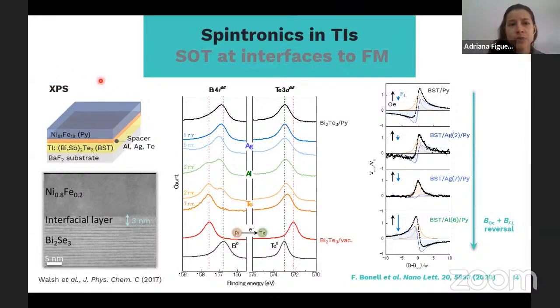So in this case, what we did was to use X-ray photoemission spectroscopy to study chemically what happens at the interface. And this is what I'm showing here. Let's take a look at what we see on these two spectra. We have the position of the spectra for bismuth and tellurium for just single atoms of bismuth and tellurium. And this is what we see for bismuth telluride, when we have the alloy. So we see that there is, of course, a charge transfer between the two, so there is a shift on each of the peaks, right?